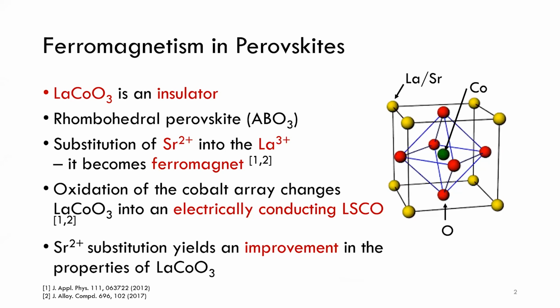But when strontium-2 plus is substituted into the lanthanum site of this perovskite, the lanthanum cobalt oxide insulator becomes a ferromagnet. This ferromagnetism observed in this material can be explained by the oxidation of the cobalt array, which changes lanthanum cobalt oxide into an electrically conducting LSCO. It can be said that the strontium-2 plus substitution yields a remarkable improvement in the properties of the lanthanum cobalt oxide.